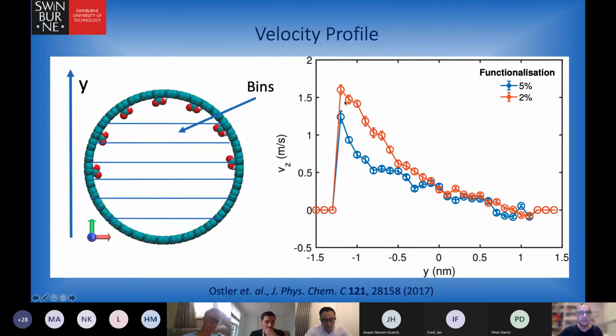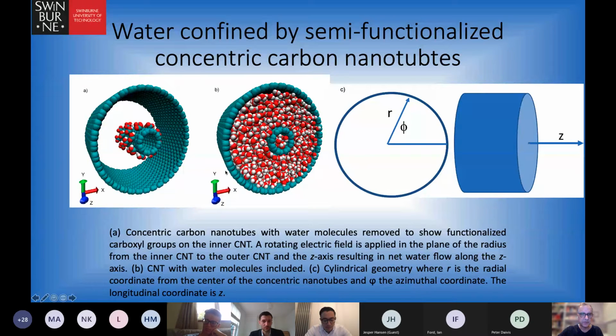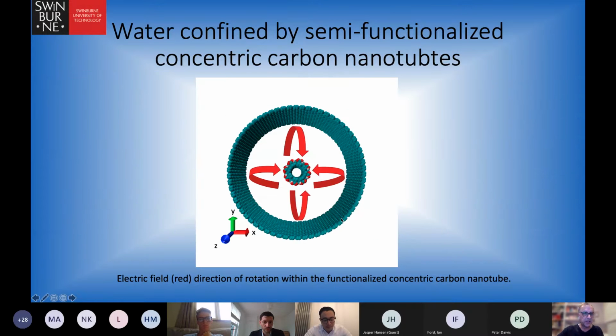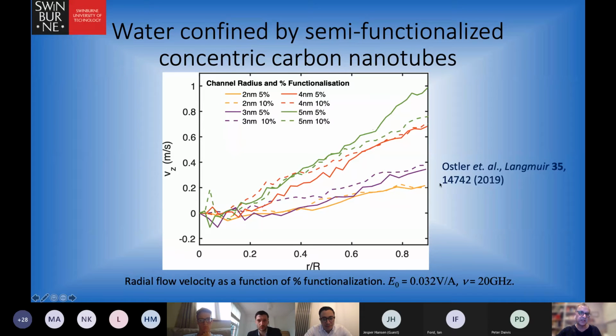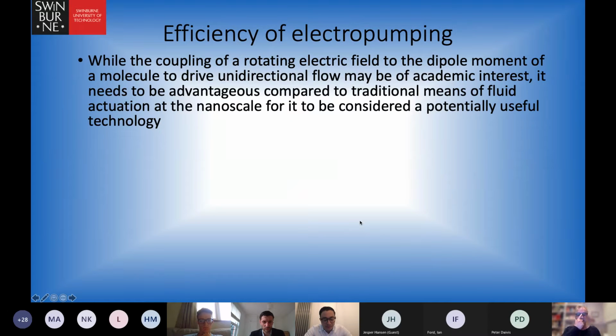This is just another way that you can view the velocity profile, simply by binning the nanotube, and you see the same results, but presented in a different way. Another way we could do this is to look at water confined to concentric nanotubes, where the inside nanotube is functionalized with carboxyl groups, the outer one remains a pure nanotube, and then you fill the gap with water. You apply the rotating electric field in the RZ plane, and you get a similar effect, okay? So you can find flow, and you can do it for different size nanotubes and for different degrees of functionalization. Okay, so that's the basic idea and the different systems that we've looked at.